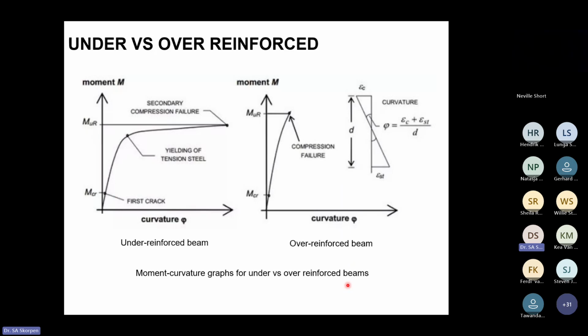Just to illustrate this further, this is a graph, two graphs just showing, again, moment versus curvature. Curvature on the horizontal axis for an under-reinforced versus an over-reinforced beam. And you can see here the crack moment, M sub CR, would be very similar for both of them, but we get a lot more ductility out of an under-reinforced beam versus an over-reinforced beam. You can see very sudden failure just after the linear elastic region here, you're getting a compression failure versus a lot of plasticity and ductility shown in the under-reinforced beam.